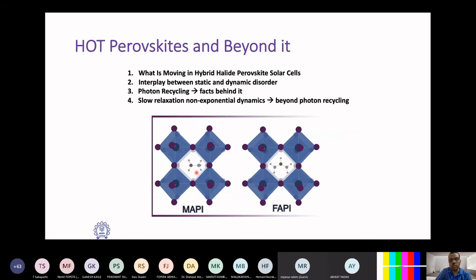Actual temperature is always more than 0 Kelvin. At any given temperature, even if you have cooled your semiconductor, this methyl ammonium or FA ion will be rotating and librating, and that will disturb these PbX6 octahedra, and that gives rise to exotic photophysics, an interplay between the static and dynamic disorder. Photon recycling, facts behind it.